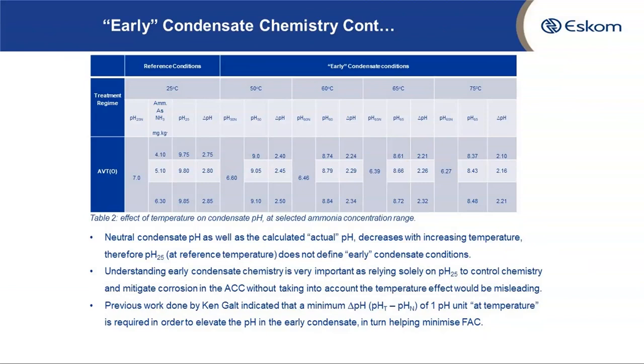Ken Galt, in his previous work, has indicated that a minimum change in pH of one pH unit at temperature is required in order to elevate the pH of the ACC condensate, in turn helping to minimize FAC in the ACCs. If you look at the table, you will see that the change in pH in almost all temperature ranges is above one pH unit, which shows that the cycle chemistry control requirements at Medupi power plant are well within the required range to help minimize FAC in the air-cooled condensers.